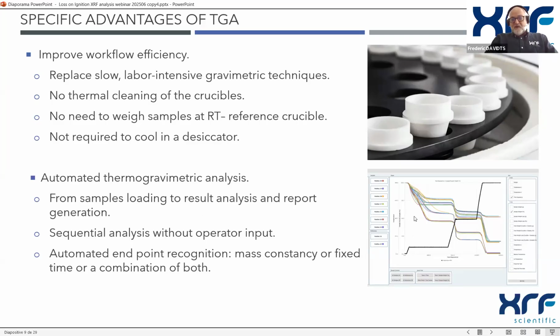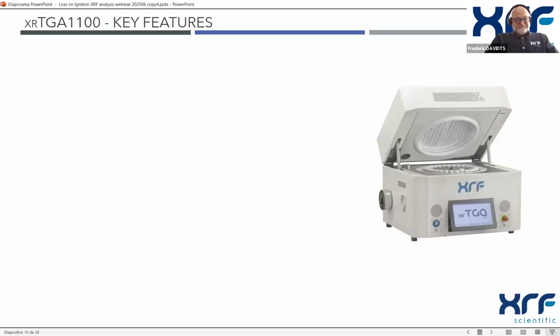So we can see in the thermograph on the right, here we have the temperature in sequential increase, and the weight loss of the different samples in percent. And of course, what is very valuable is an automated endpoint recognition. Most of the time we use the mass constancy, but for some norms, we use a fixed time, and we can even use a combination of both or other termination parameters.